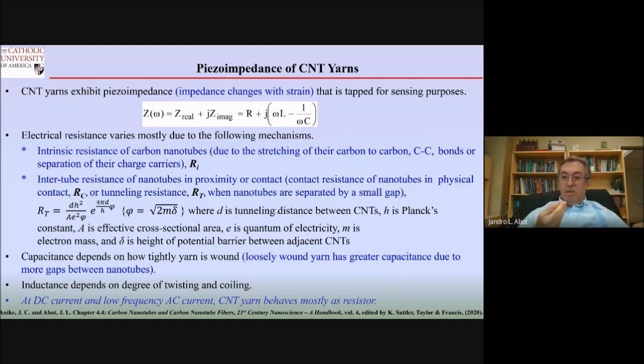These fibers are mostly piezoresistive type of sensors. But you see, I call it piezoimpedance. What's the difference between resistance and impedance? Well, the impedance includes an imaginary part. That's what you see here. This is called the reactance. The reactance has two components, the inductance and the capacitance, and that's omega, your circular frequency. If you do DC current, you only care about the resistance. But if you have an alternating current, we can vary the frequency, then you have a contribution from the reactance. Now, I have a student studying this piezoimpedance behavior going all the way to 3 gigahertz. If you go to higher frequencies, the material tends to be more capacitive. We'll talk about that later. We don't know much about it. We are the first working on that.